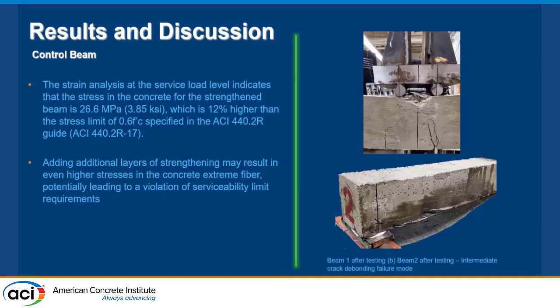So this is the picture of the failure mode. That's the intermediate crack debonding for the beam, and that's the typical crushing at the concrete ultimate fiber. So when we did the strain analysis that I would like to talk about more in the coming couple of slides, we found that the stress in the concrete was 3.85 ksi, which is 12% higher than the ACI limit, which is 60%. So even though we are getting a higher ultimate capacity, we are violating that limit ratio that controls the serviceability.